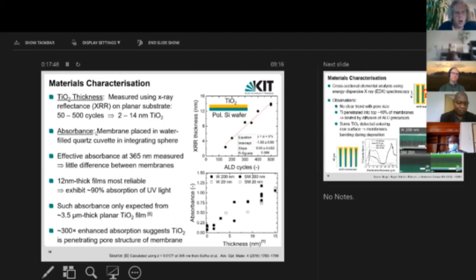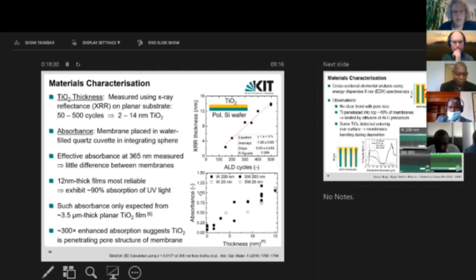The optical absorbance of these materials was measured by placing the membrane inside a water-filled cuvette, and then placing that inside an integrating sphere in a spectrophotometer. There we were measuring the effective absorbance at 365 nanometers. What you see on the bottom right-hand graph is the 2 different membranes and the 2 different pore sizes, but there's actually not a strong difference. All of them basically follow a trend: as we deposit thicker films, the thicker films also absorb a larger amount of light. We found this interesting, because you have to remember we're only depositing typically 5 or 10 nanometers of titanium dioxide, so we didn't expect the absorption to be so strong.